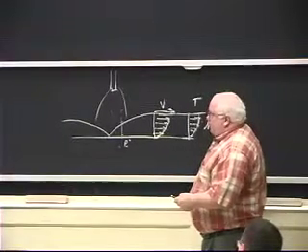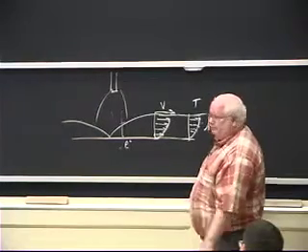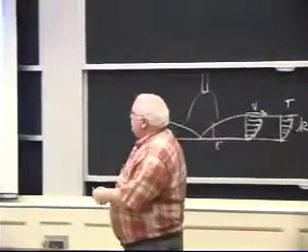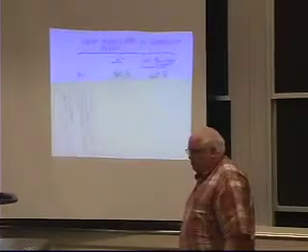And that means the gas boundary layer, the hot flame, if you will, is carrying about 20% of the heat. Okay, so 2,000 watts per square centimeter. If I have 10,000 watts per square centimeter, 2,000 is coming from convection and conduction across the boundary layer, and the other 80% is coming from the electrons. Now, if I switch gases, one of the gases that we can use in this country is helium.